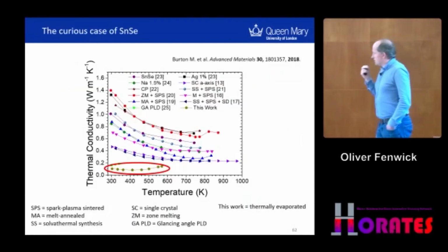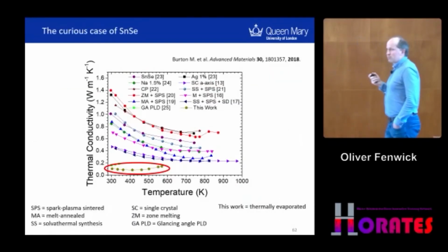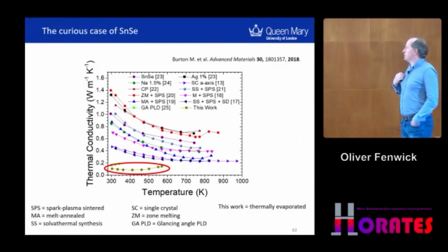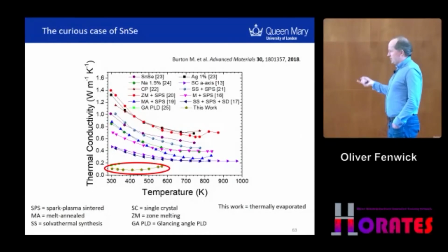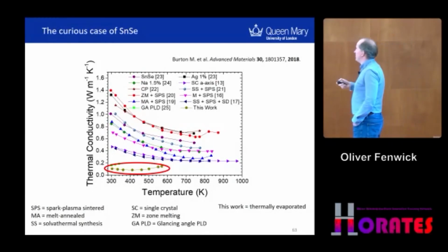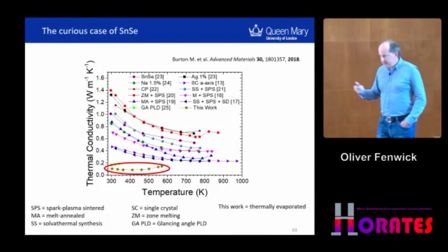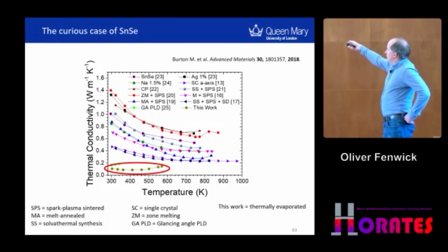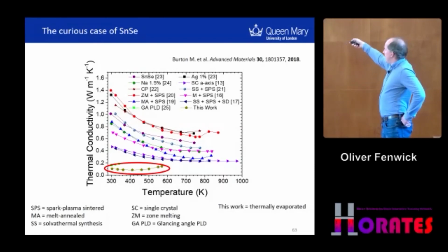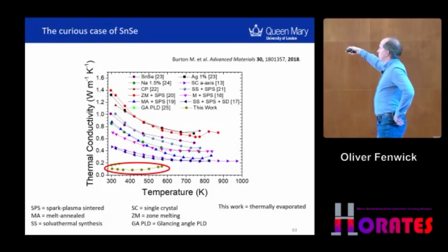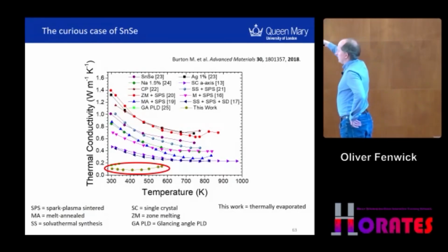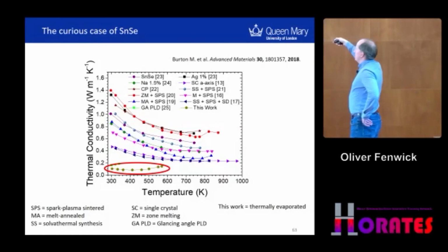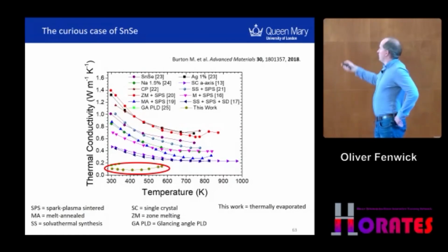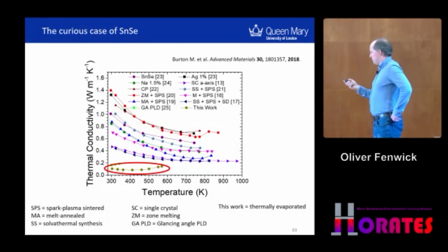This result bugged me. I was working with a group in Swansea on thermally deposited tin selenide, and we made a low power thermoelectric generator and showed we could get a nice material by this method. But the thermal conductivity was an outlier compared with other work in bulk by spark plasma sintering, melt annealing, single crystals, and so on. We were way below at 0.1, sometimes even below 0.1 watt per meter Kelvin.